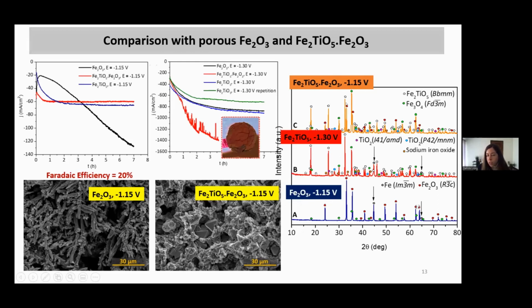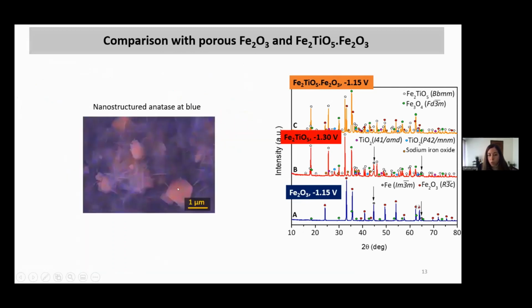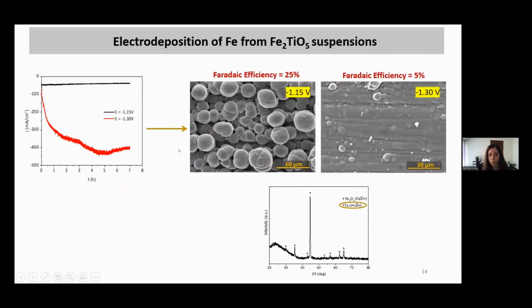So why do we have such difficulty in obtaining iron at lower potentials? As you can see here, this spongy layer is somehow covering these magnetite crystals. So it's kind of blocking these crystals from growing and being reduced to metallic iron. So we believe that this titanium oxide works as a blocker of the reduction.